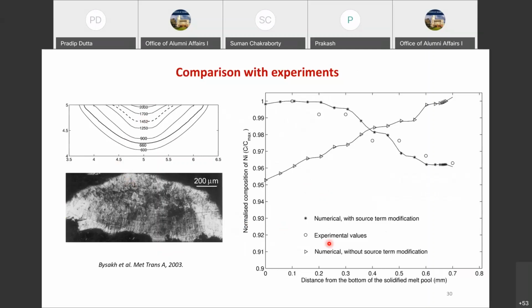Now here the circles are the experimental values, if you see. Again, the same thing, distance from the bottom of the weld pool and normalized composition of nickel in this particular case. So this is the experiment, these circles. Then we have two numerical models. One numerical model without the source term modification, that is, if we assume species mass flux at the top, our original model, then it would have predicted like this, which is in complete contrast to what the experiment is showing, these circles. But when we do the source term modification the way I just described, we found that now it predicts it correctly. So that is the power of process modeling, that can tell us.